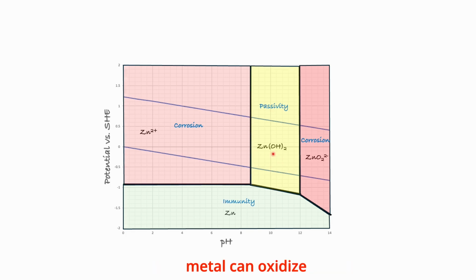even though the metal can oxidize thermodynamically, the formation of a solid zinc hydroxide film acts as a barrier between the metal surface and the aqueous environment, significantly slowing the rate of corrosion. Therefore, we refer to this region, characterized by a protective zinc hydroxide film, as a passive region, and we say that in these conditions the material is passive.